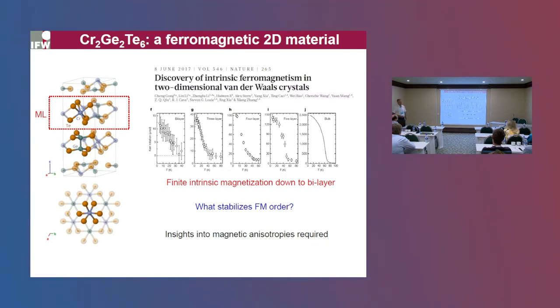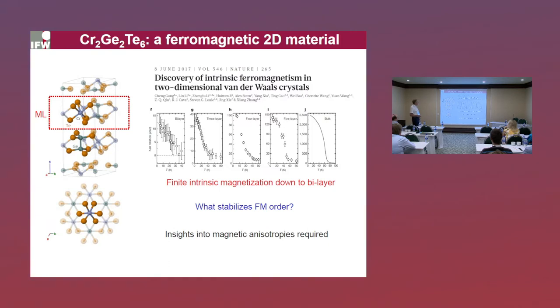That this material is a ferromagnet was known a long time ago. But recently, a really interesting work published in 2017 by Cheng Gong and co-authors showed that the ferromagnetic order present in the bulk — at a Curie temperature of about 65 Kelvin — is still present when one reduces the thickness of the crystal. Evidence came from the magneto-optical Kerr effect. The magnetization of five-layer, four-layer, three-layer, and bilayer systems still show robust ferromagnetic order, though the single layer couldn't be measured because it was very unstable. This raises the important question: what stabilizes the ferromagnetic order in this material?